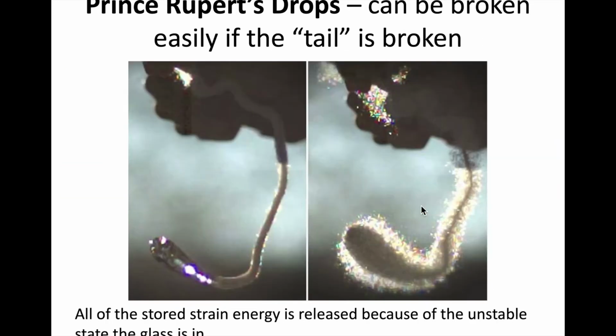However, you can actually very easily break a Prince Rupert drop, and what you do, and it's kind of hard to see here, is that if you are able to break the tail of this Prince Rupert drop, so use some type of pliers or something to break that, all of that stored strain energy from the difference in the compression and tension is rapidly released, and it propagates down the tail and causes the whole thing to shatter into a large number of pieces.